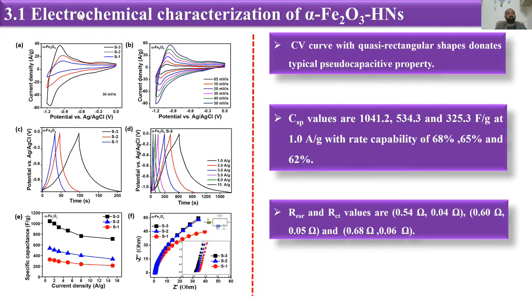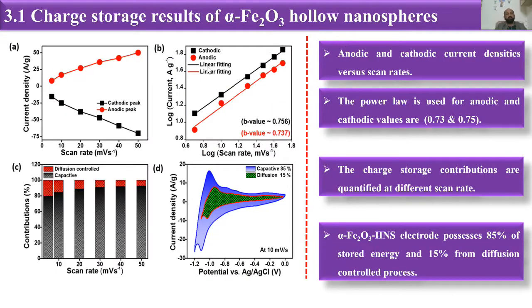Then we have done the charge storage results for our alpha Fe2O3 hollow nanospheres, and we have plotted the anodic and cathodic current densities at different scan rates, and this leads to a linear relationship that shows the good characteristics of our materials. And then we have done the charge contributions for our system at different scan rates, and we have got the capacitive charge ratio, which was dominated over the diffusion ratio of our system. So we have compared all of these results.